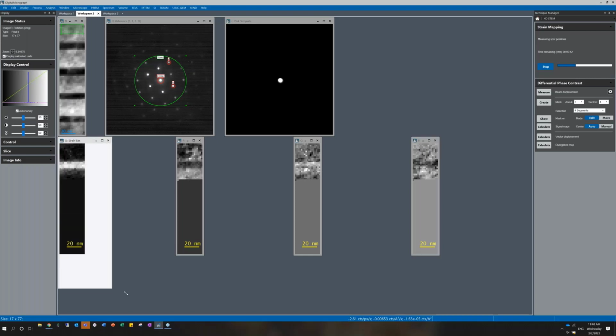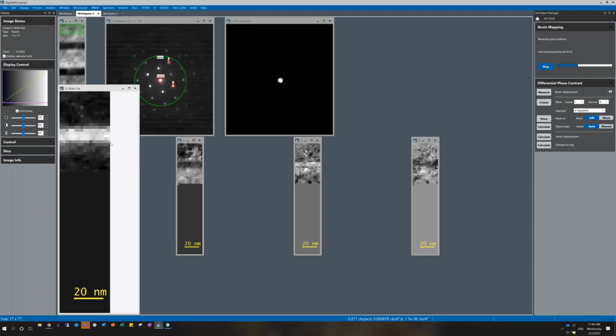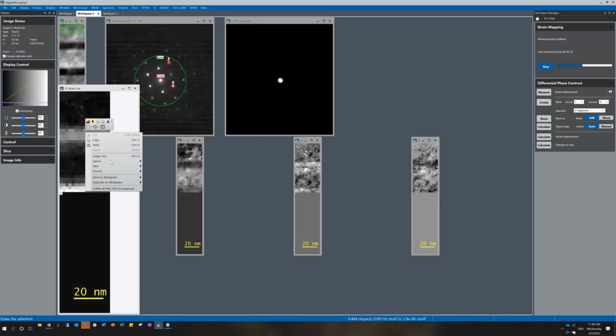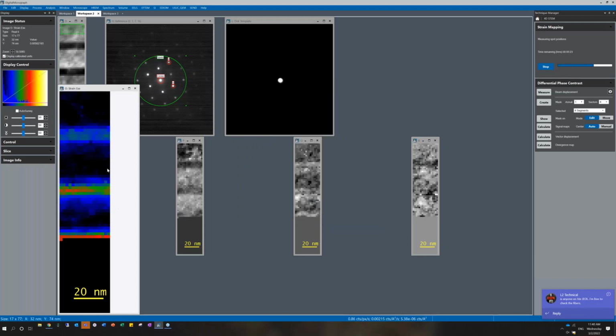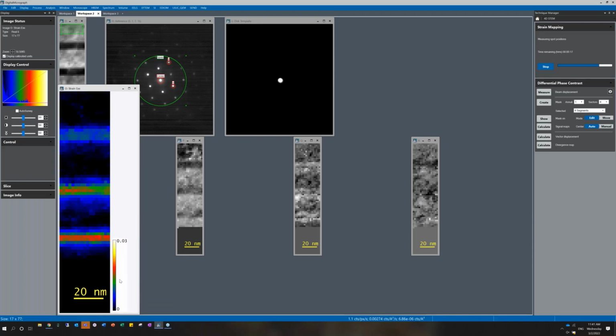This is the direction for which I expect to have strain as I go down the layers. I can go here and change the contrast so that we can better see, and I can actually make it color. I can also add an intensity bar here for you. So you can see as we go down the layers, the amount of strain is increasing as the amount of germanium is increasing in the sample.